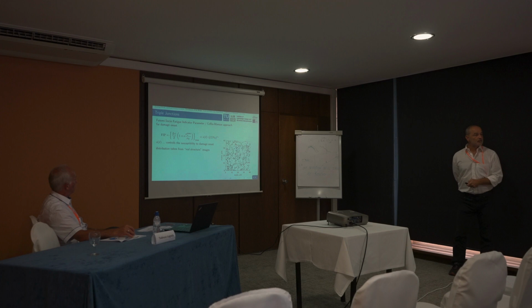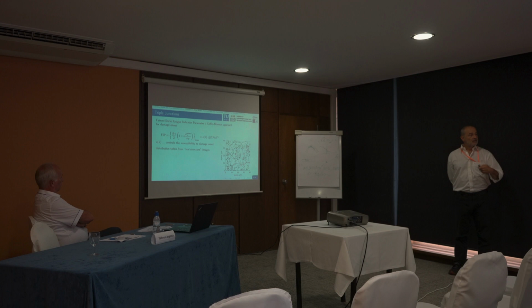And then we interpret this as a Coffin-Manson behavior, where you see the number of cycles to failure, the exponent, and this factor. And what we introduced here is this S of x. This means at certain positions x, we can reduce the number of cycles until failure sets on. So this is a parameter we can play with and see how this works.